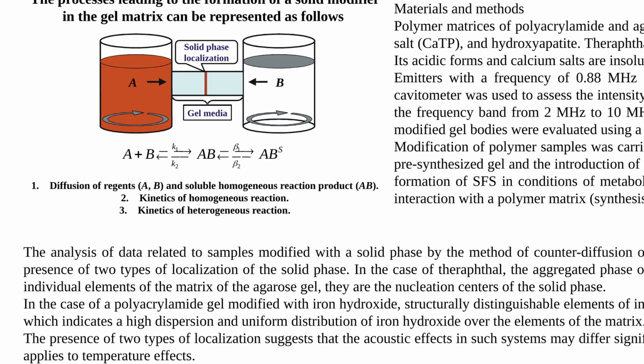The polymer samples were modified by 2 methods. The first was counter-diffusion of reagents, forming a poorly soluble compound inside a pre-synthesized gel. The second was the introduction of solid modifiers during gel synthesis. Counter-diffusion provides a model for the formation of solid phase sonosensitizers under conditions associated with metabolic acidosis in tumor tissue. It is also useful for studying the interaction between the solid phase and the polymer matrix.